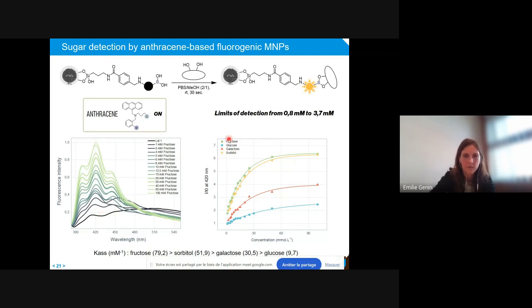We did this for several sugars, three of them, as well as sorbitol, and we were able to draw curves comparing the intensity to the initial intensity. Here you can see the increase, and importantly, it's a significant increase. So the detection is working, and that's even better in this case than in solution.